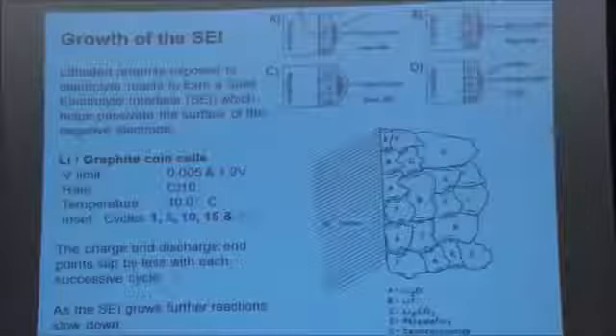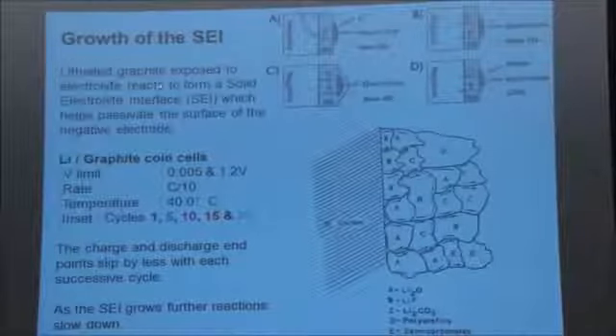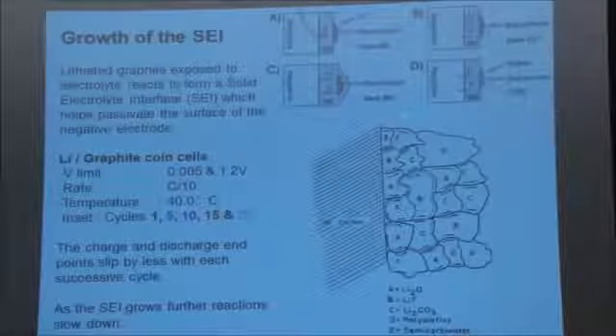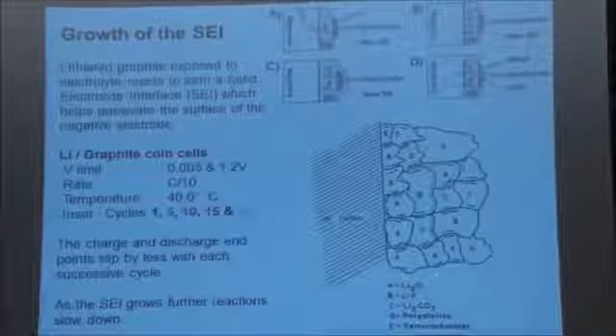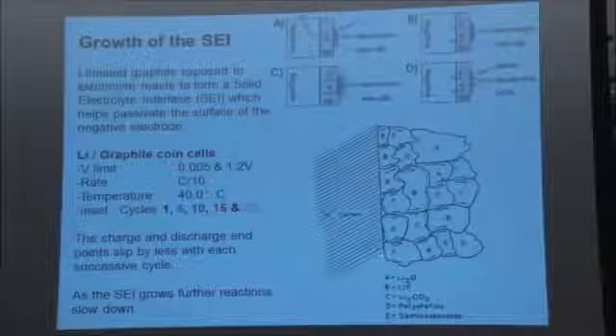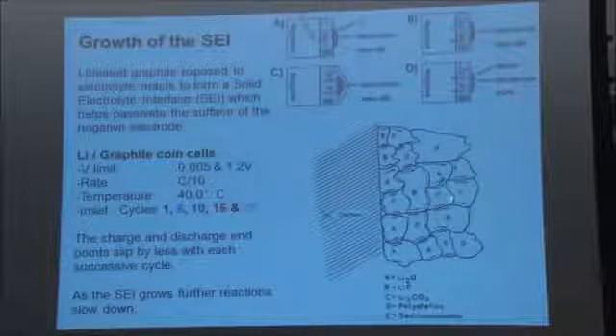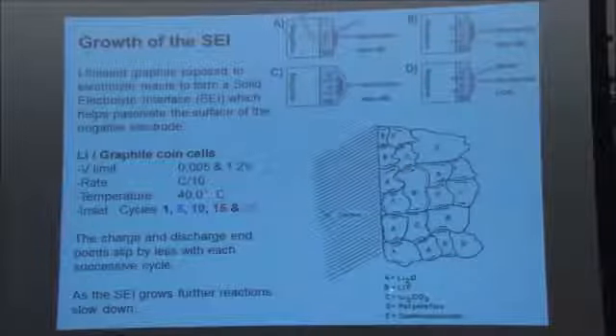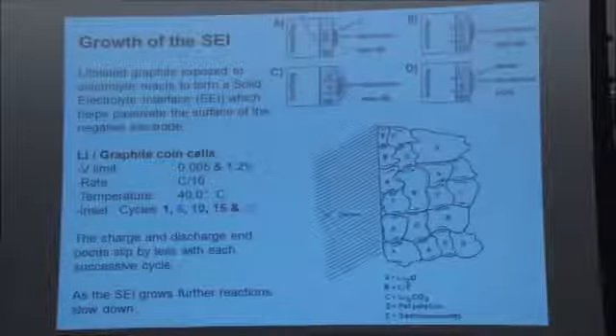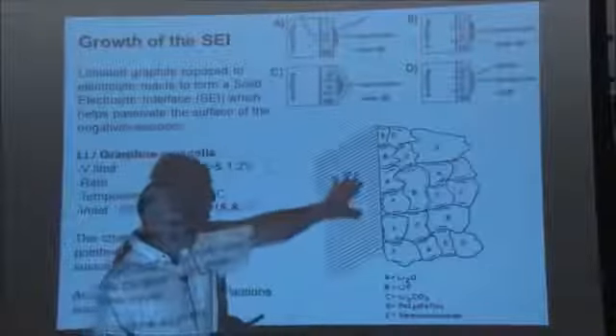As I mentioned, when the graphite becomes intercalated with lithium and it's exposed to electrolyte, it reacts with the electrolyte. And a film of reaction products forms on the surface, called the solid electrolyte interphase, or SEI. This is a picture from a paper by Emmanuel Peled showing the structure of the SEI. It's a heterogeneous mess comprising inorganic and organic components. But anyway, as this forms, it slows down the reaction between the lithium in the carbon and the electrolyte solution.